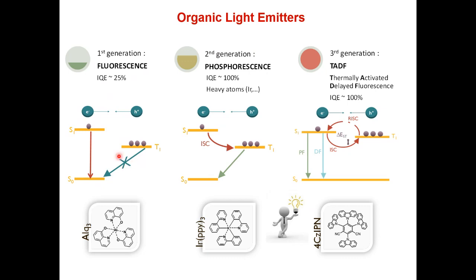So there was then a second generation. And the idea was very bright. The people said, okay, there is a class of material which can basically favor the phosphorescence going from the triplet to S0. And with a very specific ingredient, which is called spin-orbit coupling, which is a relativistic effect, you can go from T1 to S0. And the trick to get this process efficient is to have a very heavy atom, like a metallic atom in the center, like here, it's an iridium.